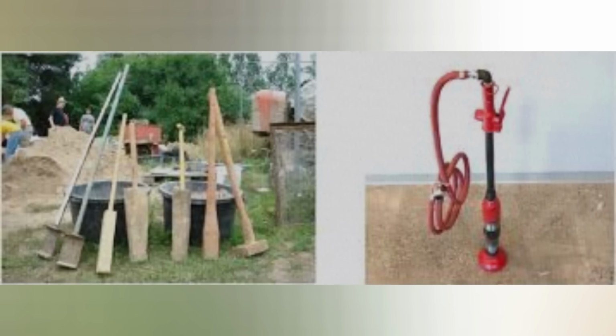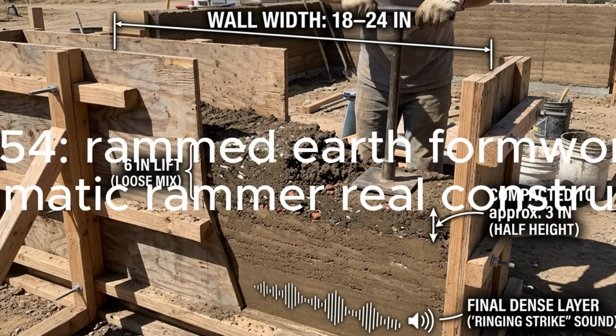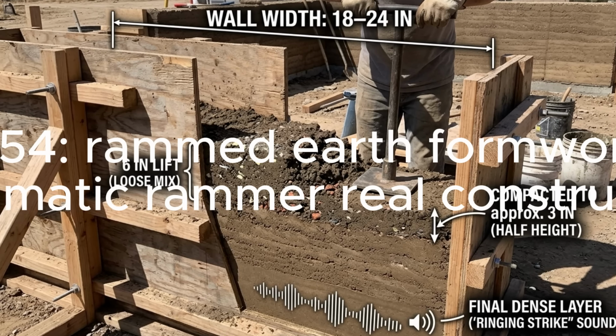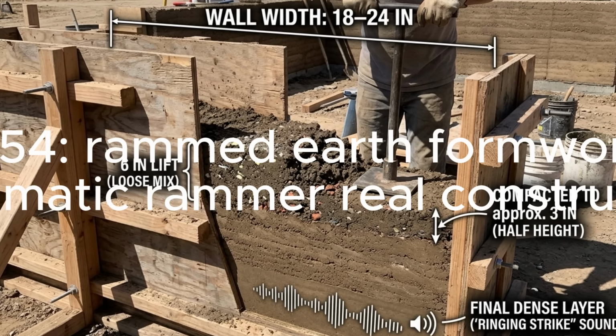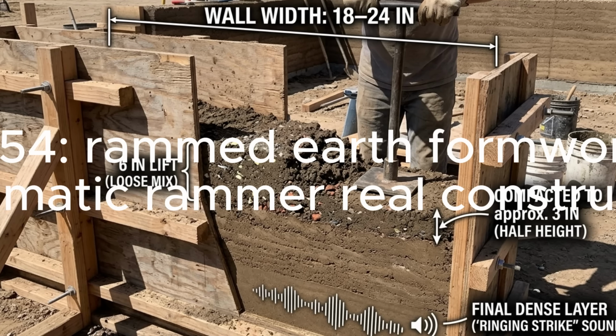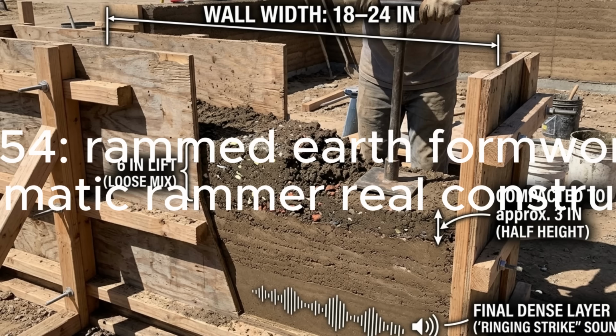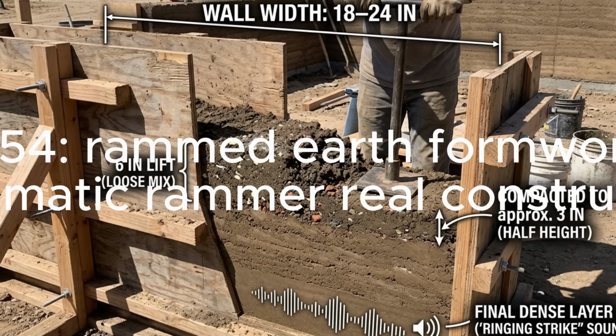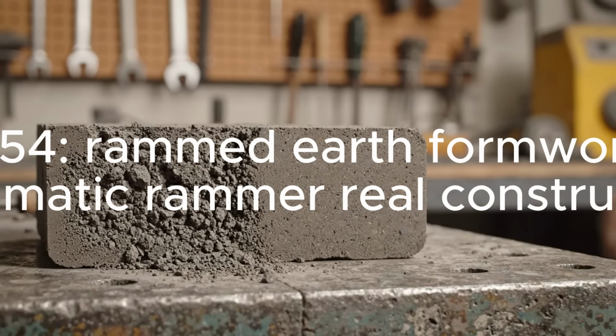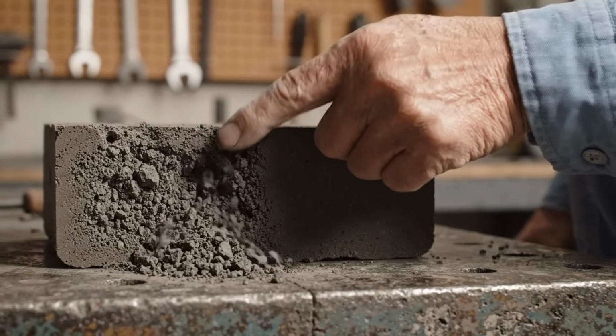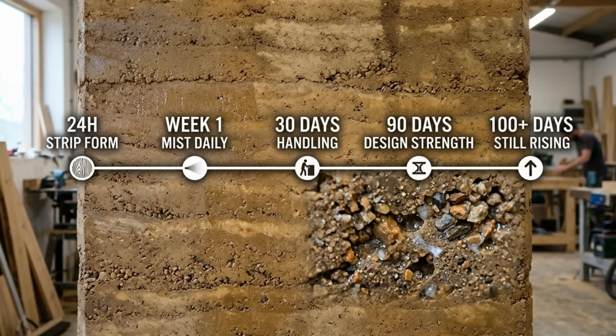Step 4. Formwork, tamping, cure. Set up parallel boards 18 to 24 inches apart, braced firmly. For garden walls under 4 feet, exterior-grade plywood works. For taller walls, use steel reinforced framing. Pour the damp mixture in 6-inch lifts. Tamp each lift, by hand or pneumatically, until the volume compacts to roughly half its original height. The sound of the rammer changes from a soft thud to a sharp, ringing strike when the lift is fully compacted. That sonic signature is your signal to move on. Under compaction is the single most common failure mode in modern rammed earth projects. After 24 hours, strip the form and reset for the next section.